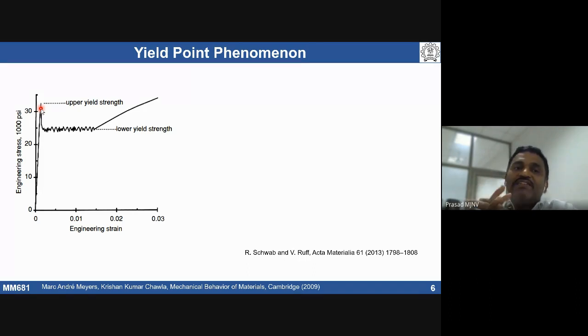So that interaction gives us an atmosphere called the locking atmosphere, also known as the Cottrell atmosphere. People call it the Cottrell atmosphere because he was the first one who pointed out that when there are interstitial solute atoms, those can lock the dislocations and form an atmosphere around them because of the stress field present in the dislocations. So the material, which already has dislocations, has some of its dislocations pinned down.